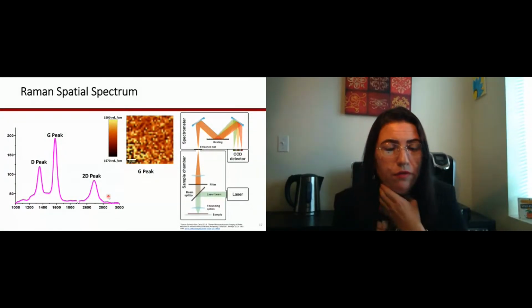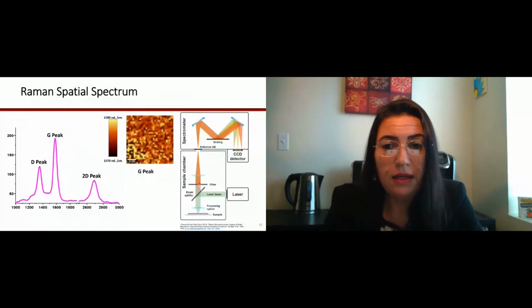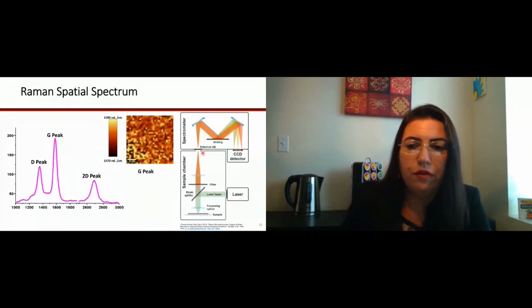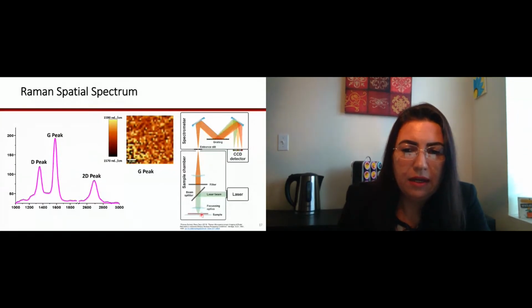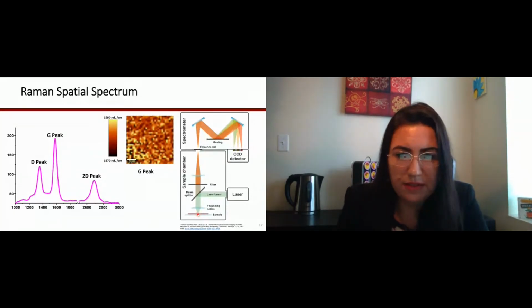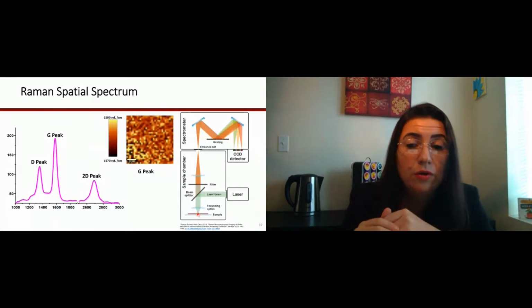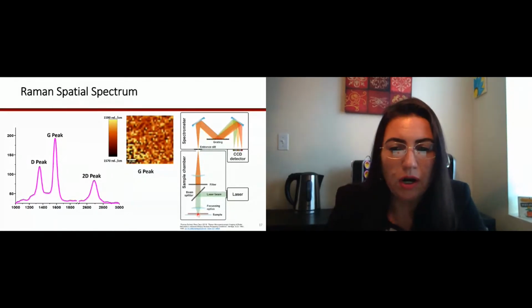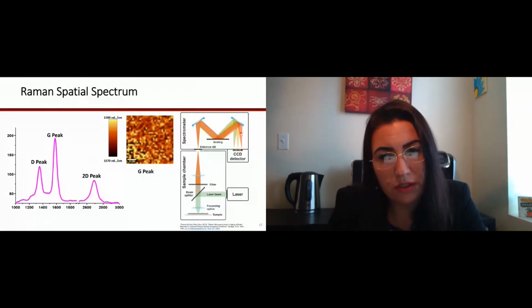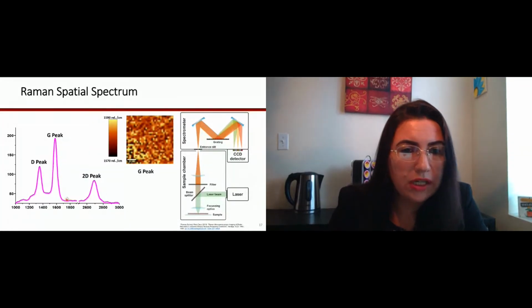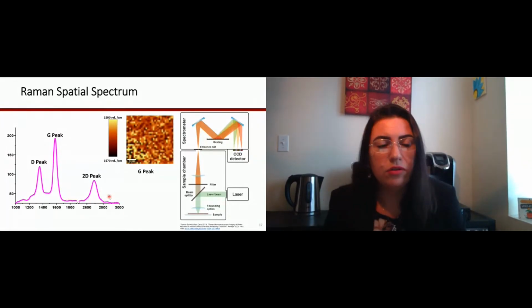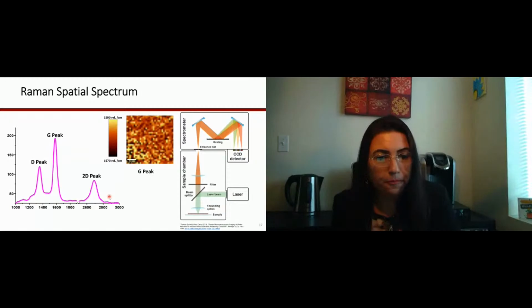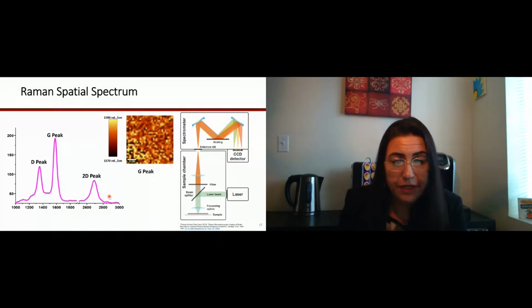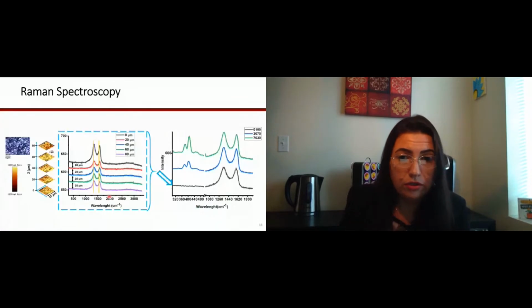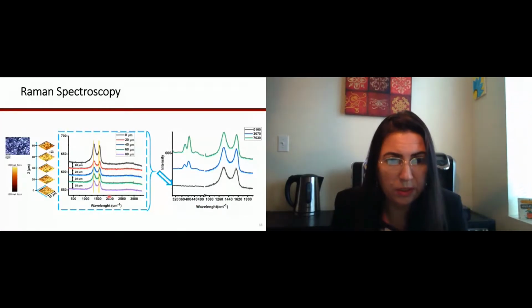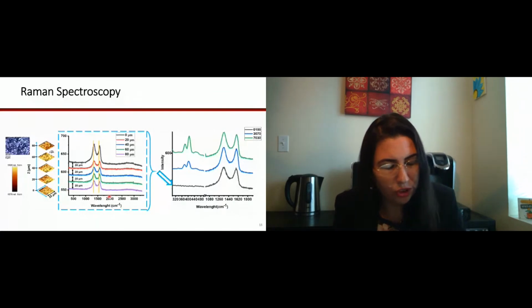So what is Raman, for people who are not familiar with it? It is a laser that uses photons. The photon shines through the sample, and when it shines here on the bottom of the sample, the material will vibrate either in plane or out of plane. And once the photon returns back, the detector will give specific peaks, that are the fingerprint for graphene. And in our case, I had MoS2 and graphene oxide because I did lyophilization, the freeze.